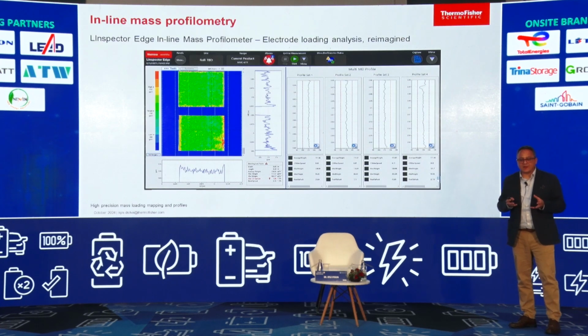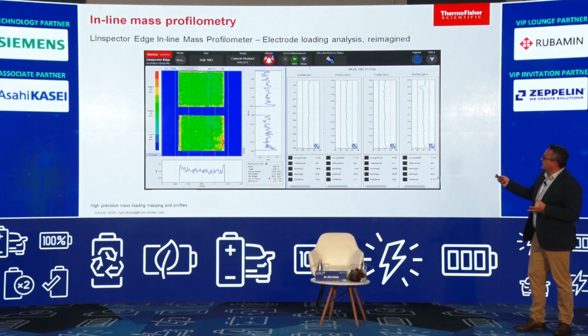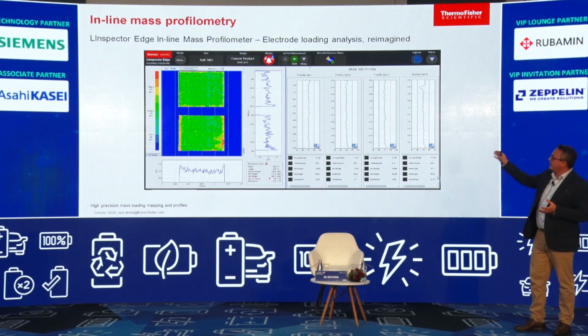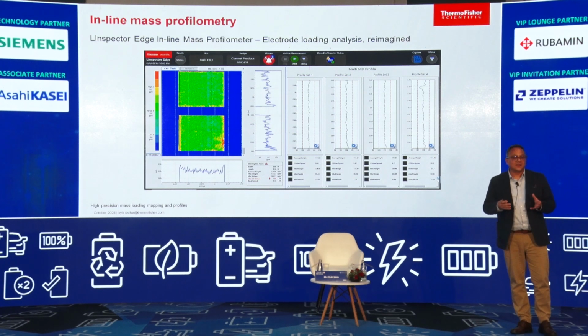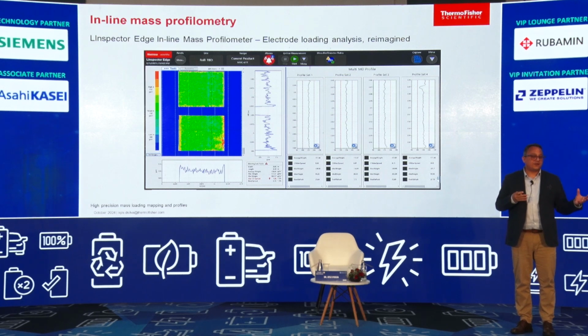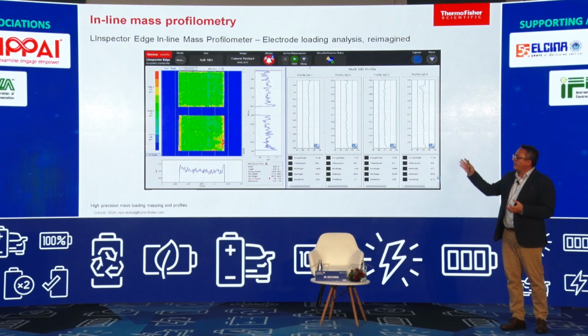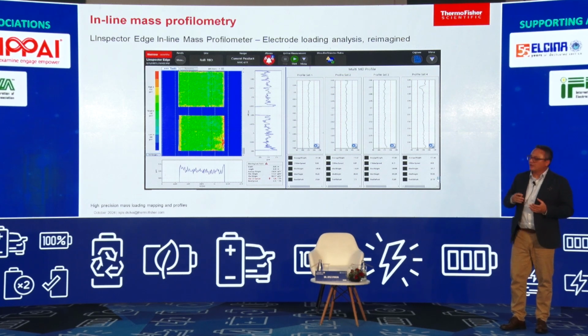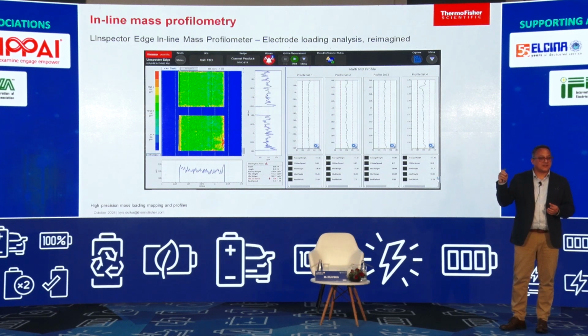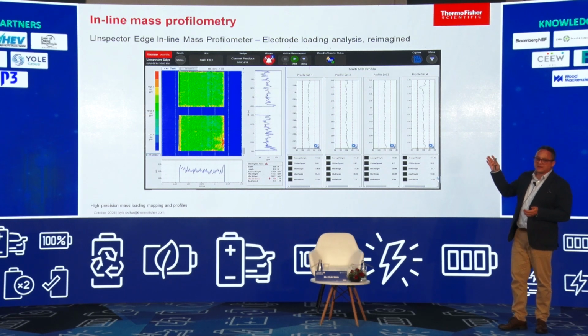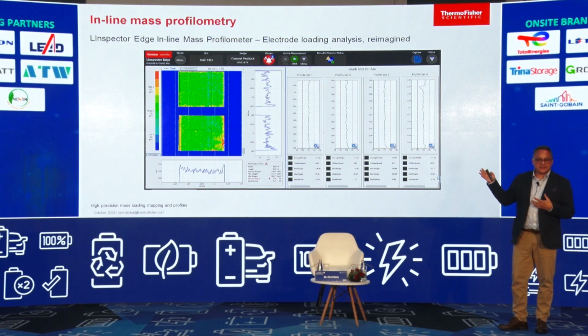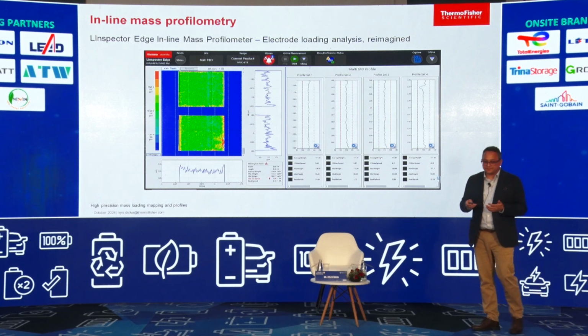So this is how the data is represented. You can see in the machine direction on the right-hand side the thickness and basis weight of all of the coated material. On the left-hand side, you can see the heat map. Really, you could see down to the millimeter resolution of any thick or thin patches through the material. You can automatically archive the data, and you can also create flags and alarms if any of the material is out of specification.